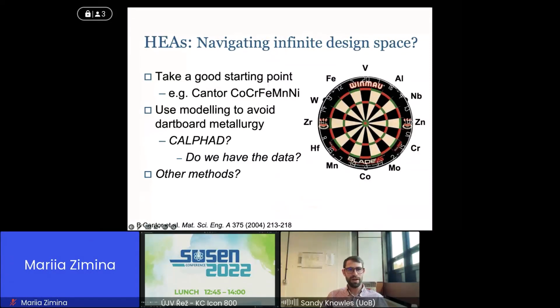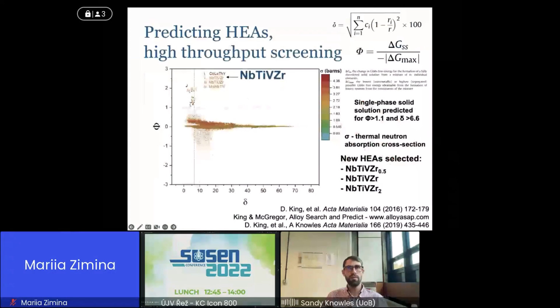We can use things like CALPHAD thermodynamic predictions, or maybe some other modeling methods. All of these have challenges, particularly in CALPHAD, as we were saying in the tungsten-based superalloys. If you don't have the prior data, you can't make a good prediction. So we've been looking at some high throughput modeling screening methods. I'll put my hand up, I'm an experimentalist. I was working with Dan King and Simon Middleburgh on this. They're the modelers, and trying to use this.